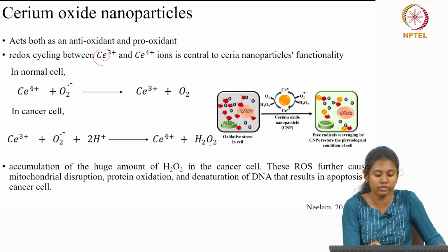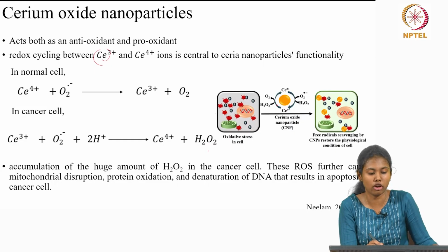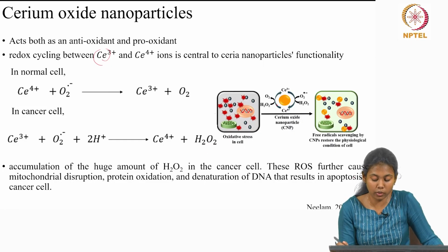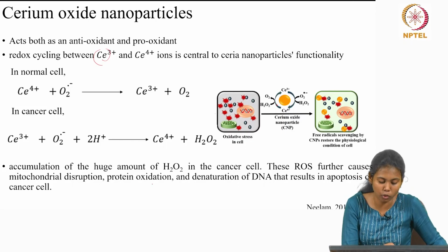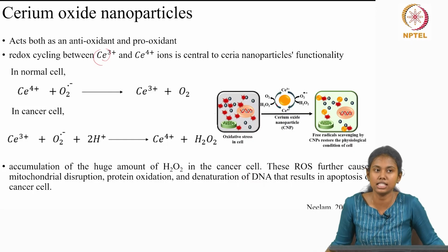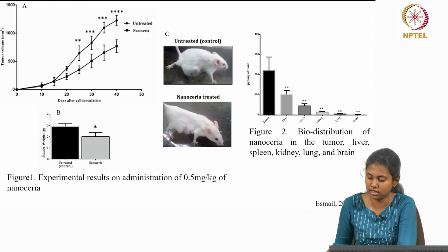The further reduction of this H2O2 is also catalyzed by the catalase activity of cerium oxide nanoparticles, which leads to apoptosis of the cell by various mechanisms like mitochondrial disruption, protein oxidation, and denaturation of the DNA. So, this is the mechanism by which cerium oxide nanoparticle targets cancer cells.